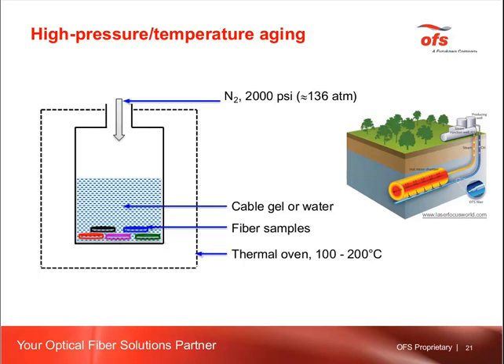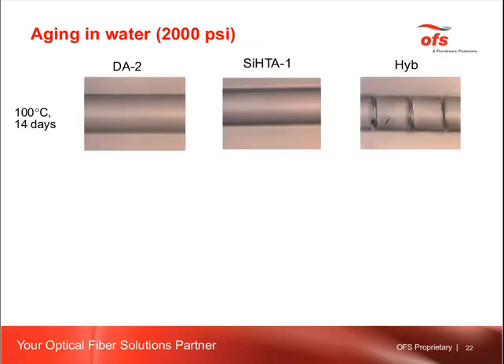Really harsh testing: short pieces of fiber can be immersed in a fluid like a cable gel or water. Then we can apply a high pressure, up to 2000 psi, and we also can place this in a high-temperature oven, so we can increase the temperature to values of 200 degrees C or even higher, and that would mimic a real downhole application of an optical fiber. I'm going to show you some of the examples.